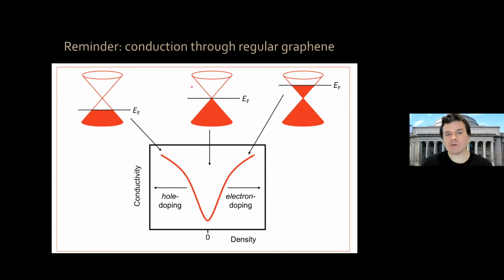So now let me remind you, what does conduction through graphene look like? Okay? Just regular graphene. If you look at conductivity versus charge density, if you have your Fermi energy here deep in the valence band, you have lots of holes and graphene conducts very well. If you put your Fermi energy deep in the conduction band, you have lots of electrons, and graphene conducts very well. In fact, it's the best conductor in the world, okay? If you put the Fermi energy at the charge neutrality point, there are very few charge carriers, and graphene conducts poorly. So the conductivity of graphene versus density has this V-shaped behavior, okay? And this has been seen by thousands of groups around the world.